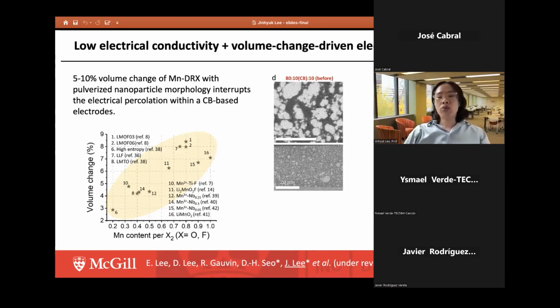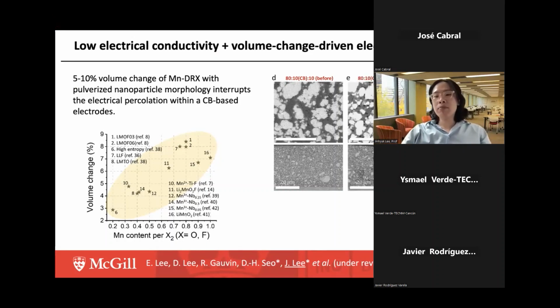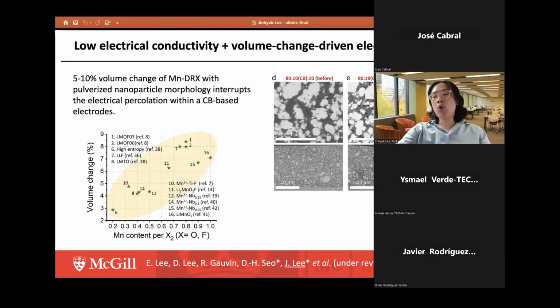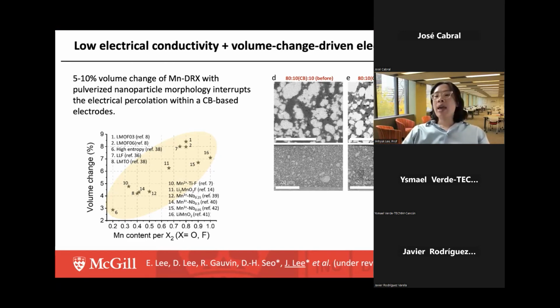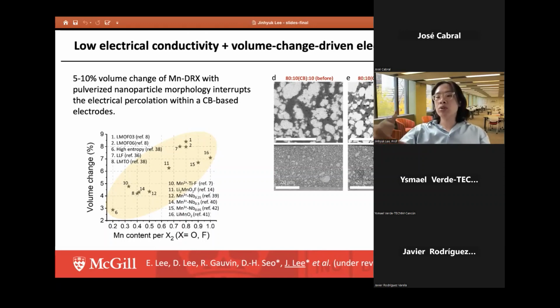Now if you look at the cross-section, this is the electrode before cycling. Now, if you cycle 5 times, you start to see pores generating in the cross-section, and you also start to see cracks developing across the electrode film. And now if you go to 80-10-10 after 20 cycles, you see the pores start to agglomerate, and you start to see a large crack develop across this electrode film. So all this problem has to be addressed at the electrode film level.